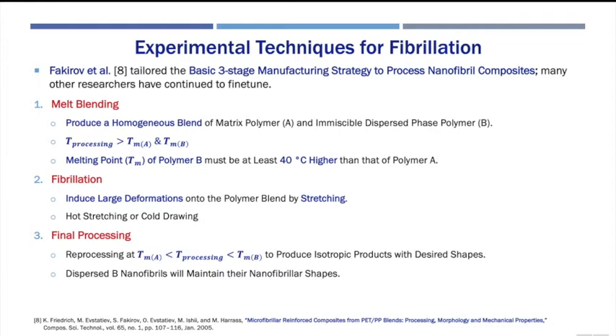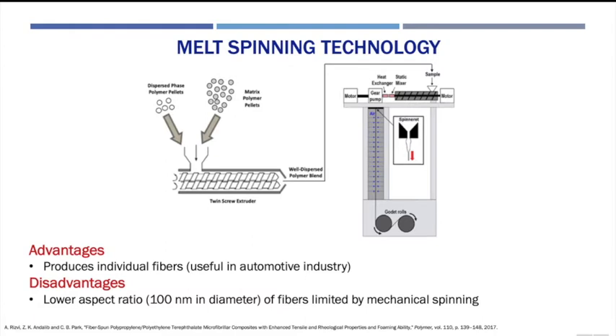Here, I'll outline three high-throughput methods of in-situ fibrillation. These three methods are melt spinning, melt blowing, and spun bond. Melt spinning is a displacement control technique used to produce fibers by Godet rotation. This uses a twin screw extruder to melt a well-dispersed polymer blend. The molten polymer is then flowed through a spinneret die and then stretched by rollers. Although these fibers possess good mechanical properties, this is a multi-step process that can often involve substantial operator intervention.